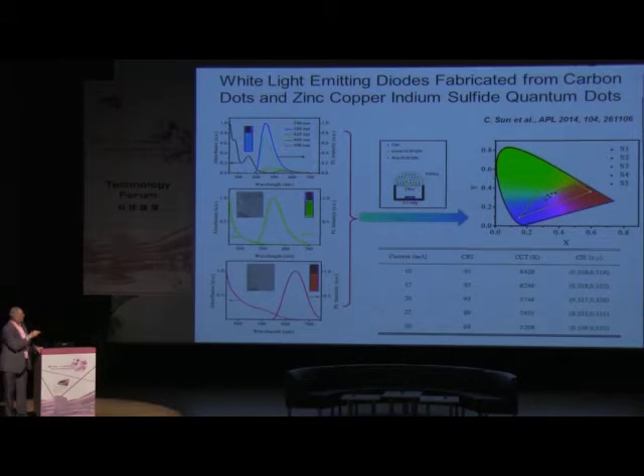And here we used a very simple, straightforward RGB concept, which is red, green, blue color. So combination of red, green, blue color placed together on a single device would give us white color as a result. And this is one useful way how to make white light-emitting diodes. So we combine blue color from carbon dots and green and red color from quantum dots of this particular composition, mix them together in different proportions, again excite them optically by UV light, and then we can get white color with different shades, like yellow shade, bluish shade.